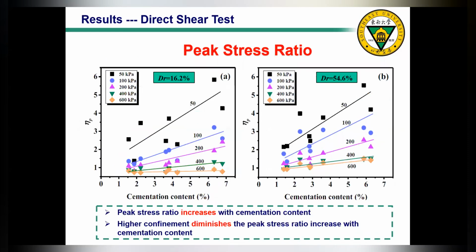Then we systematically summarize the peak stress ratio results and correlate them with the cementation content. The left-hand graph is the low initial density case, and the right-hand graph is the high relative density case. Firstly, the peak stress ratio increases with cementation content. This is true for all samples. It means that cementation can help improve the peak shear strength of the calcareous sand.